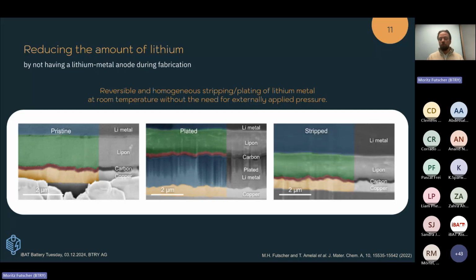And of course, we can remove the lithium again by stripping it, and then the lithium is completely gone here. And this now allows us to build an anode-free thin film solid-state battery. And in the publication, we even showed that we can do this up to current densities of 8 milliamps per square centimeter without leading to short circuits.